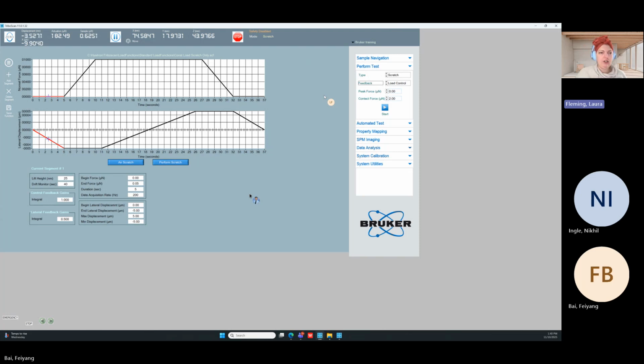So let's go ahead and walk through this load function, segment by segment. In this first segment, this 0 to 5, my normal force is doing nothing, but I'm moving -5 in x. During this next segment, my x is doing nothing, but I'm loading into the sample. During this next segment, I'm loaded into the sample, but my normal force remains constant while I scratch. Then I move to the +10. Then we stay at that +10 while we unload to the sample surface. And then we come back to 0 in the lateral direction. So this is move backwards, load, scratch, unload, move back to 0. Pretty straightforward. Are there any questions about this one in particular?